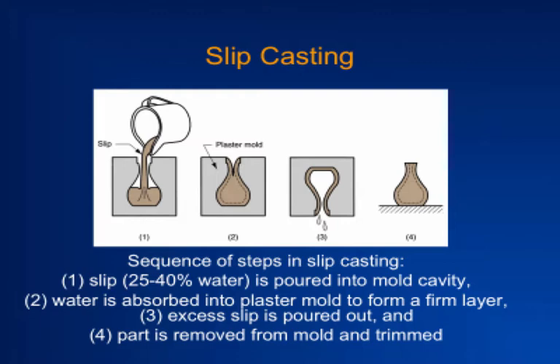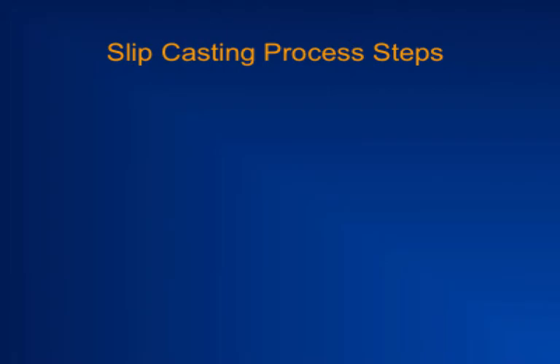So you pour some material into the mold, and you swirl it around for some time. As water comes out through the porous mold, a solid layer is formed, and you can pour the excess material back into the pot to fill a new mold. And you can create hollow shapes in this manner. So that is called slip casting. After it's dried completely, you can go ahead and fire the material.